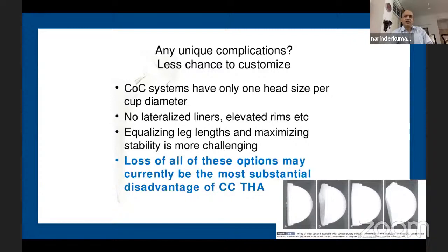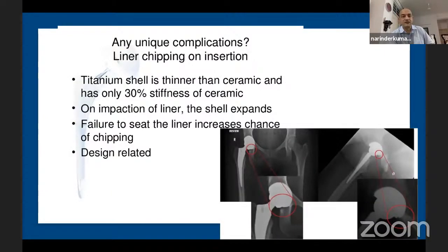And then ceramics, with their only one head size per cup diameter, no lateralized liners, no elevated rims. We have all these options in the poly. They decrease our chances to customize intraoperatively. You need to have a perfect pre-op plan and implement it there, because equalizing leg lengths and adjusting the offsets, vertical and horizontal, will become a challenge. If you're using a ceramic liner, we can't use poly for it. Even for stability, there are no elevated liners available. So that places you at a disadvantage.